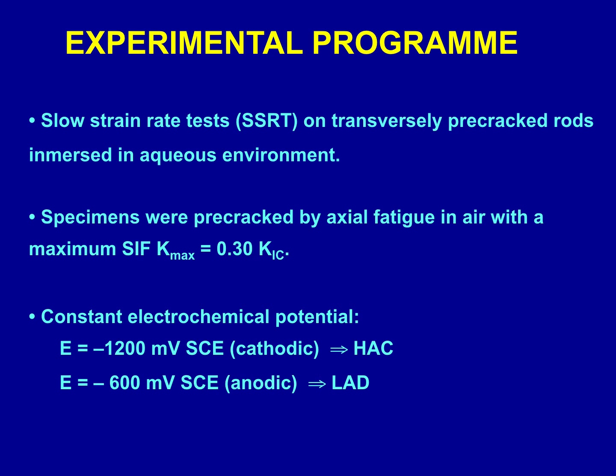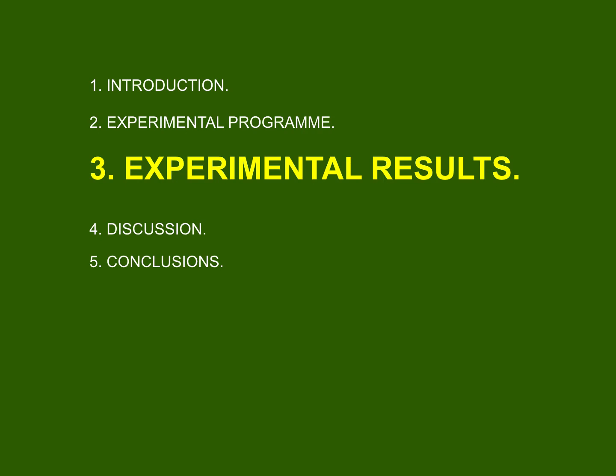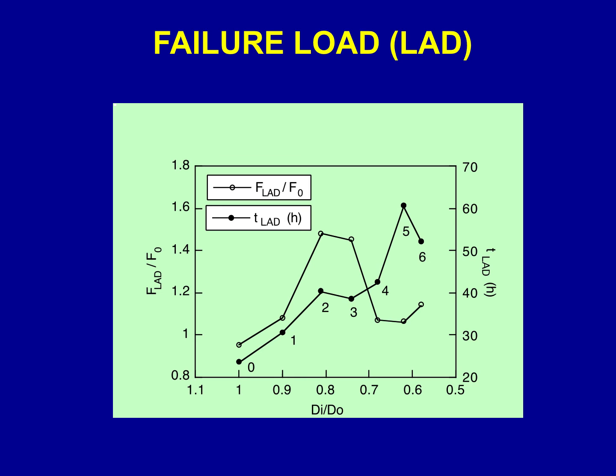minus 1200 millivolts versus saturated calomel electrode. That's cathodic and is associated with hydrogen-assisted cracking, and the potential regarding the analysis in this paper, minus 600 millivolts versus saturated calomel electrode, anodic potential in which the mechanism is localized anodic dissolution, or pure stress corrosion cracking. The experimental results are presented in the form of a plot of failure load in localized anodic dissolution or pure stress corrosion cracking, normalized by the failure load in air, vertical axis in the left hand side.